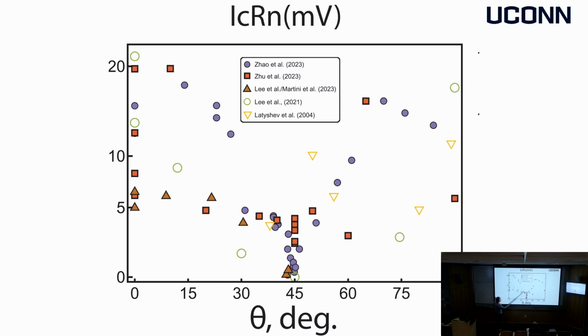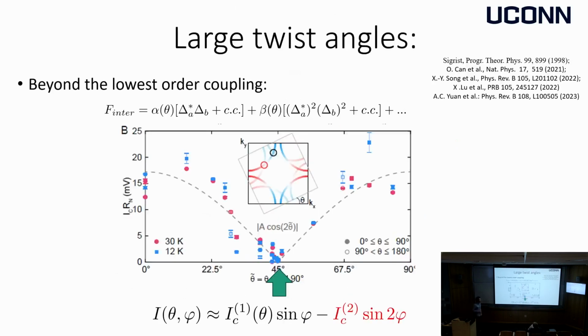The overall idea is that there is still a suppression at 45 degrees, but there's so much scatter that one needs to be really careful about those interfaces. And the triangles, I recently talked to that group, and they improved the quality of the interfaces, and the value of the critical current seems to be going up at zero twist. So I think there is ongoing progress in making those interfaces better and better, and I think it's important, especially for the things that I will discuss in the second part of my talk. Okay, so far, basically what I tried to convince you of is that cuprates are D-wave. Perhaps that's not so very interesting.